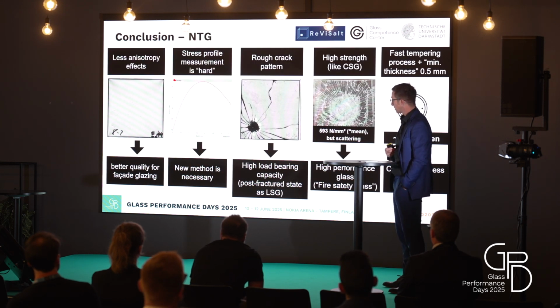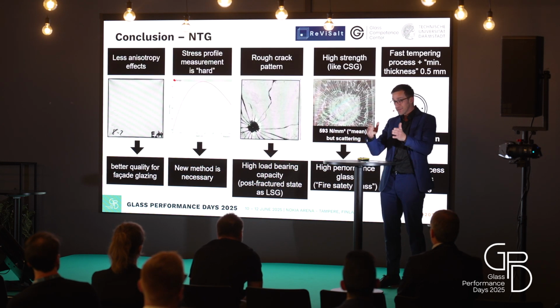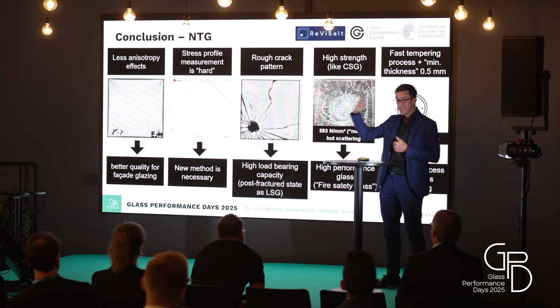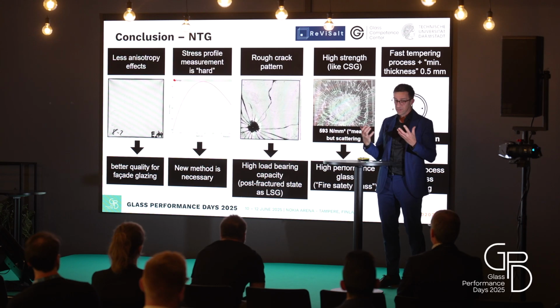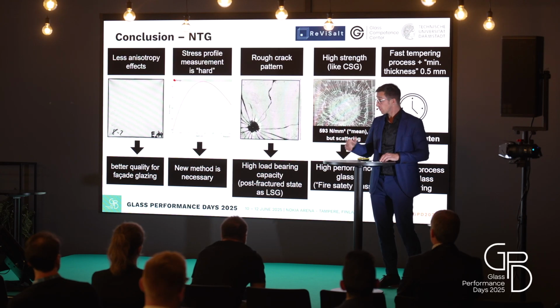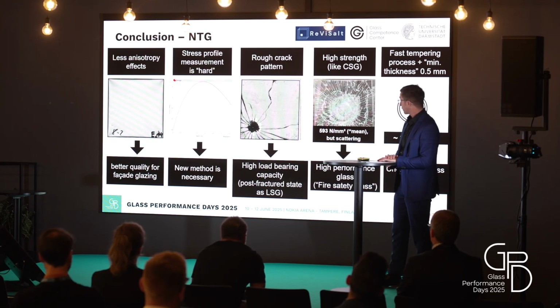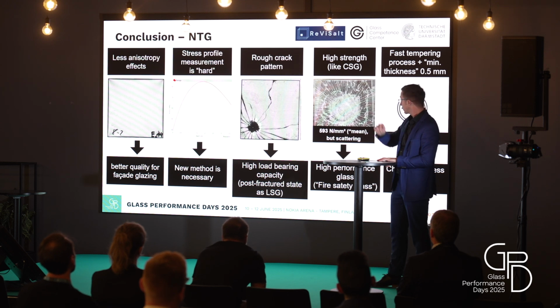I want to conclude now. With the novel tempering process, we have less anisotropic effects. We had a better quality for the glazing, and also with the roller waves, because the process is totally different. We had no issues with the roller waves. The measurement of the stress profile is hard. We need new methods for this. We had a rough crack pattern. This is pretty cool for a high load-bearing capacity in the post-breakage behavior state.